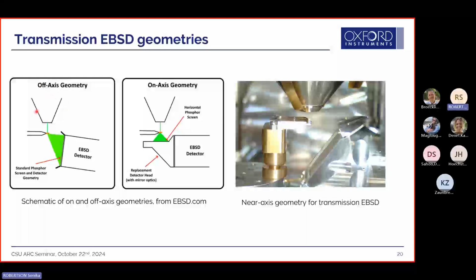So if this is your electron beam coming through this gun column, this would be your sample holder. This little red thing right there is your lamella, and your EBSD detector is right on the side. So you're getting the signal generated from the underside of the lamella. That's what you're doing. A few months ago, Oxford just launched an add-on. It's an attachment to the EBSD.